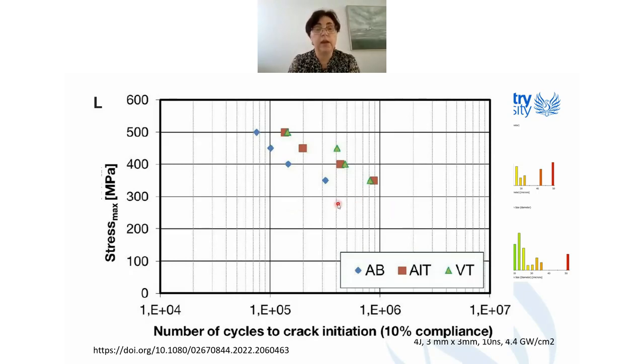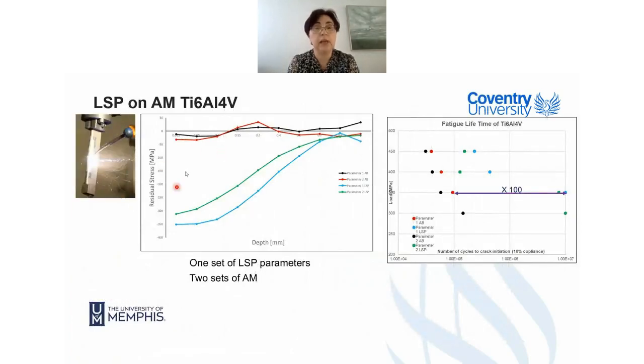reduce the manufacturing time by using thicker layers in the printing, and also minimize the influence of the powder quality. So here I'm showing the data on LSP on additive manufactured Ti6Al4V. And from the graph, you see that we were able to imprint residual stress quite deep, over 1 millimeter.